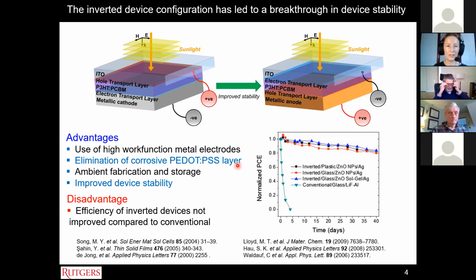And so the advantages of using high work function metal electrodes like gold or silver, for example, in inverted devices is that you create better stability and you also eliminate the corrosive PEDOT:PSS layer, which also is a cause of instability in organic optoelectronic devices. It also potentially enables ambient fabrication and storage and, as I mentioned, improves device stability. The problem is the efficiency is not as good typically in the inverted devices compared to the conventional because of control of this interface, as well as just the lack of studies that have been done to develop these inverted structures or devices.